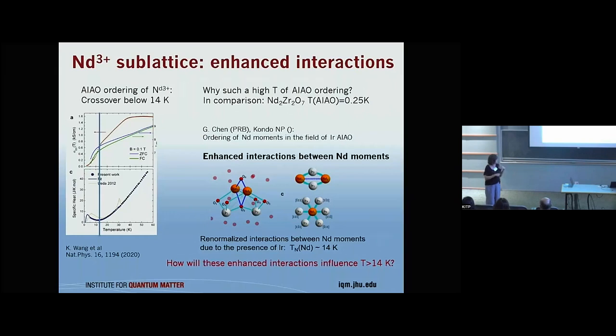So basically, yes, we suggest this very high energy scale, and then we have to make more crystals, which we're doing now from the experimental point of view, and look at this high energy scale. The argument pro is that it's a frustrated system, and we see ordering of neodymiums at high temperatures. Also, the ordering you see is opposite to the ordering of your exchange. But so there is a little bit of experimental evidence, and I think we have to look for more.